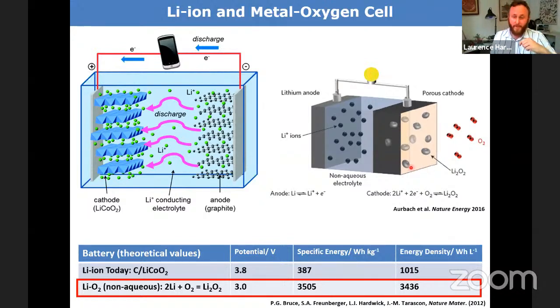We combine the three components and we grow, ideally, lithium peroxide in the lithium oxygen battery case, and this grows within this porous conductive network, and to some extent it can be reversed. And so the challenge is to try and get this chemistry to be much more reversible.